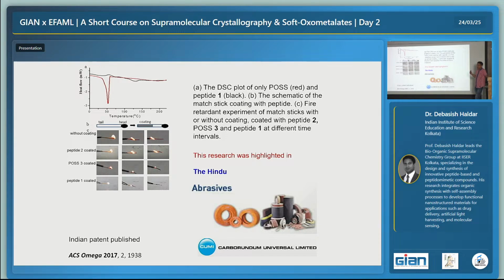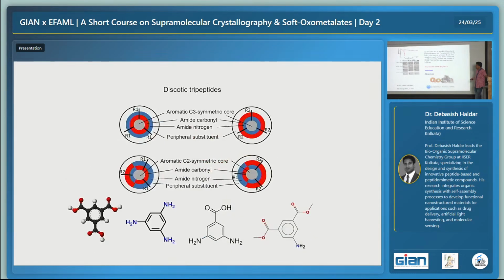I had a little information that polyoxosiloxane can prevent fire. When we developed this, we took a matchstick and coated half of it with our compound. Without coating, the matchstick is completely burning. With peptide only, the flame reduced, but the matchstick again completely burned. With only polyoxosiloxane, the flame is reduced, but still the matchstick is burned. But with our hybrid compound, it stopped at the point of coating. So we can take care of fire now with this compound, and we have patented this, and we have a collaboration going on to put this compound as a utility compound in the market in future.